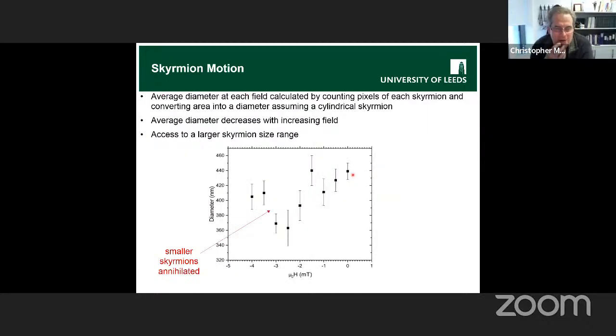I just want to briefly mention this idea of the field. At the time there were models that said that the angle that the skyrmions move at with respect to the current should depend on their diameter. So we wanted to see if that was true. To adjust their diameter, as I said, you can do that with the magnetic field. We apply this negative field, we should squeeze these skyrmions down, and that's what we saw up to a point. That point's about here, where some of the smaller skyrmions get annihilated, and then the average size jumps up again a bit because you've only got the bigger ones left. But it does work that you can squeeze them and make them smaller.